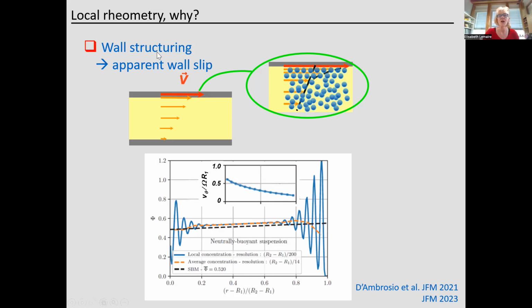And the first point that can invalidate macroscopic rheological measurement is the wall structuring that is observed in non-Brownian suspension. So when you put a suspension between two walls, the particles tend to form layers near the walls, and in this layered zone, the viscosity of the suspension is much lower than the bulk viscosity. So that means that if the viscosity is much smaller here near the wall, the shear rate is much higher than the expected shear rate, then you have a kind of apparent wall slip.